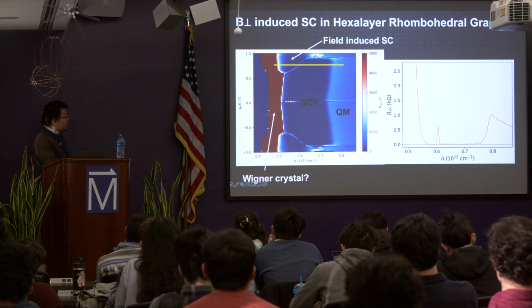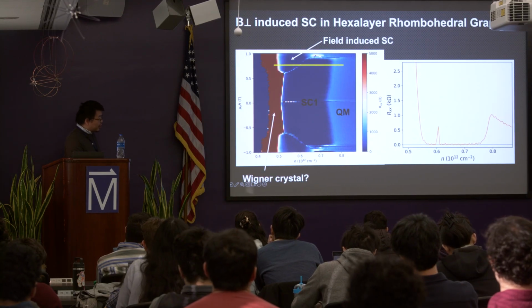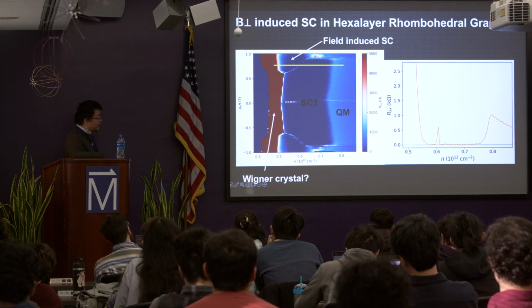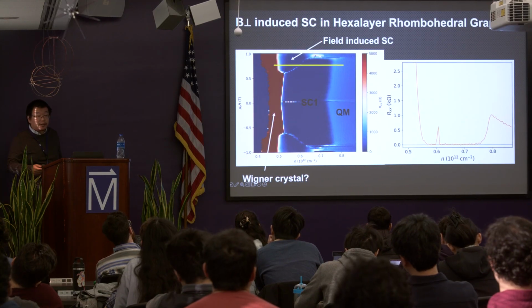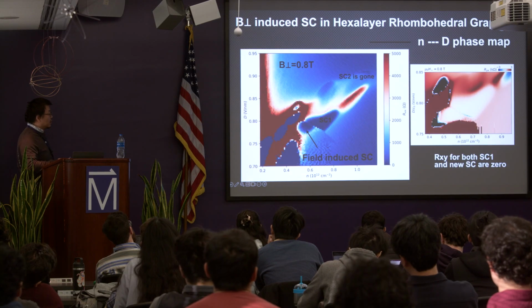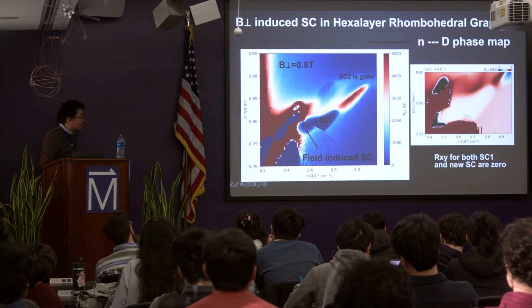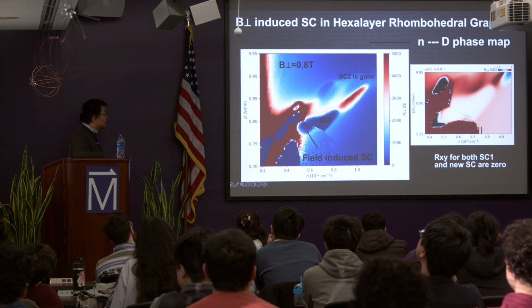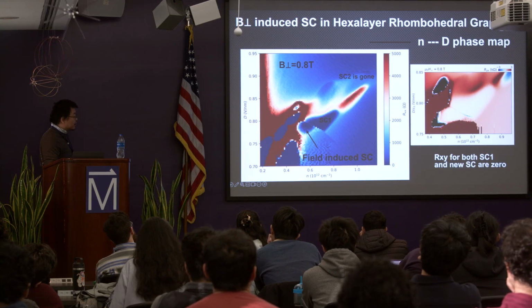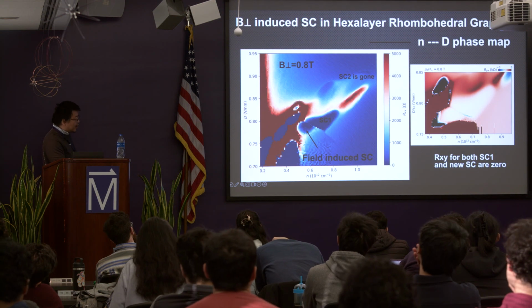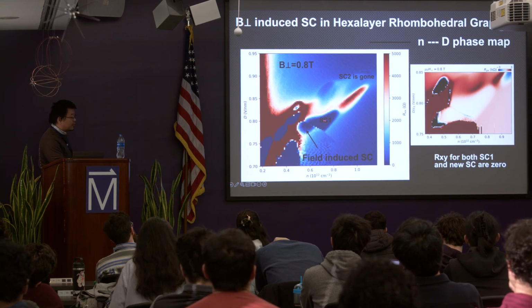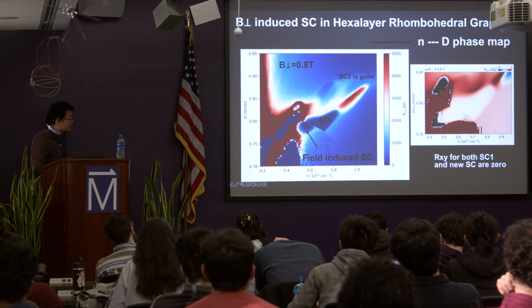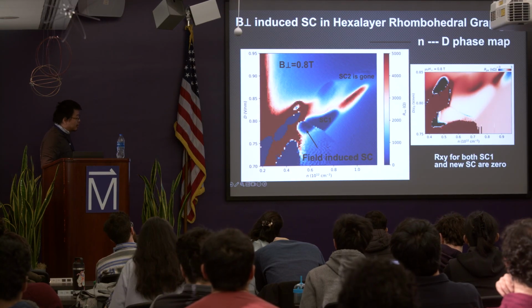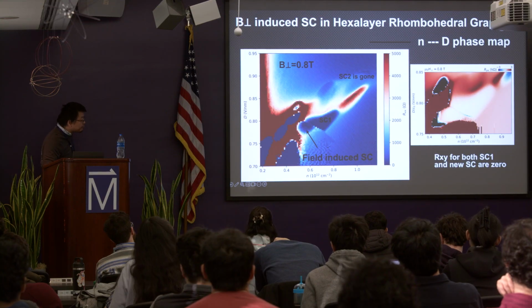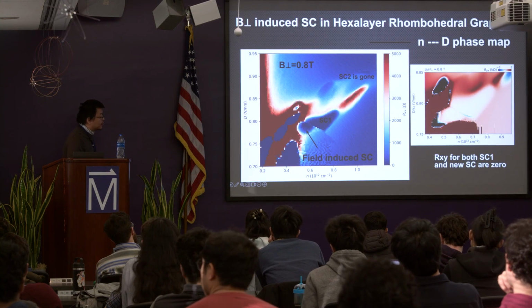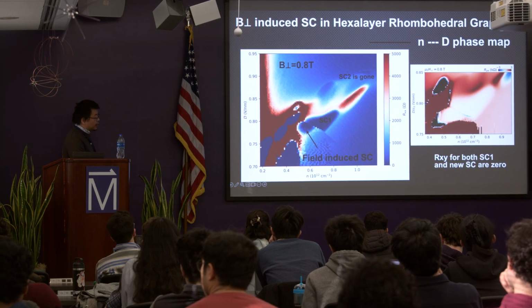If we do a line cut here, we can see it's actually a pretty good zero resistance on both sides, and you have a very sharp phase boundary that separates the 2 phases. If we take a closer look at a complete phase diagram by density and electric field, you can see it looks like it's being cut in half: part of it is the SC1 we've seen at zero magnetic field, and the other part is the new superconducting phase coming out. And of course, you can also check the Hall response, and on both sides the Hall response is 0.